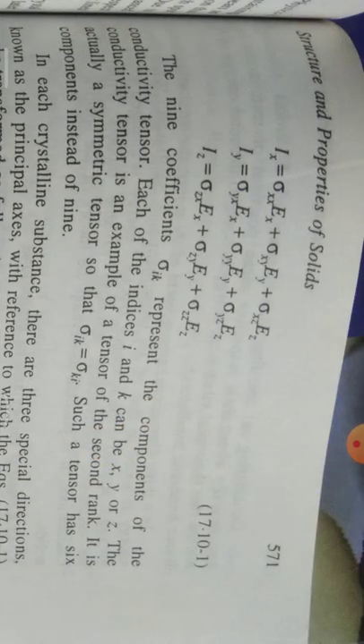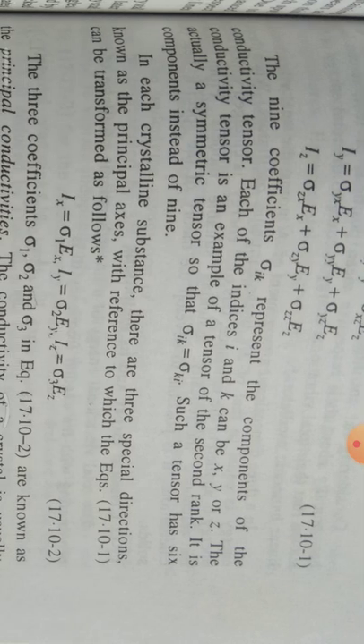Ix is equal to sigma xx Ex plus sigma xy Ey plus sigma xz Ez. Iy is equal to sigma yx Ex plus sigma yy Ey plus sigma yz Ez. Iz is equal to sigma zx Ex plus sigma zy Ey plus sigma zz Ez. The 9 coefficients sigma ik represent the components of the conductivity tensor.